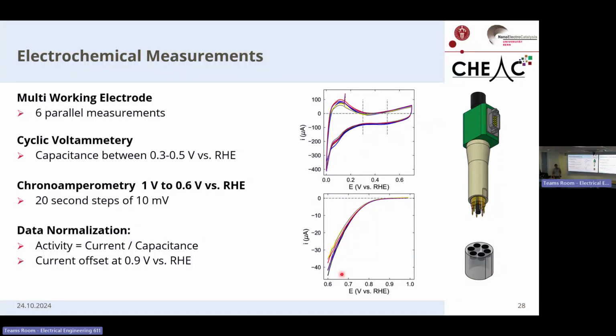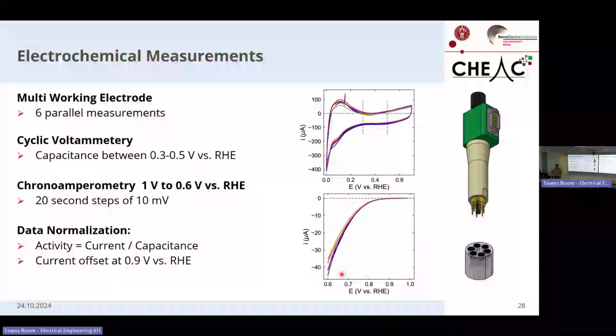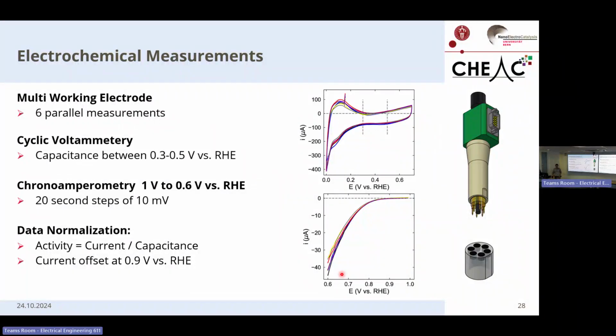Does it make it faster then? Yes. Because you get 6 independent statistical curves instead of 1 big statistical aggregate. If you then have to take into account loading, we normalize in this case by the capacitance, and you also get a better way to check the reproducibility of the electrocatalytic performance.